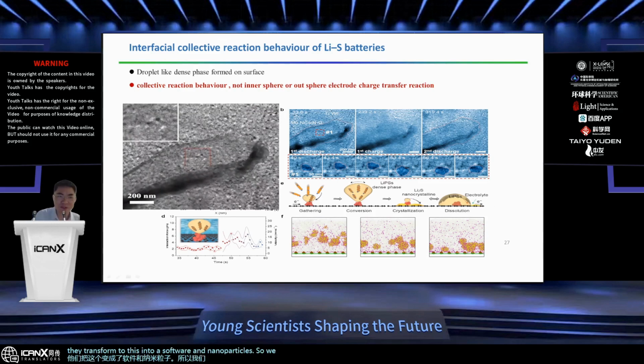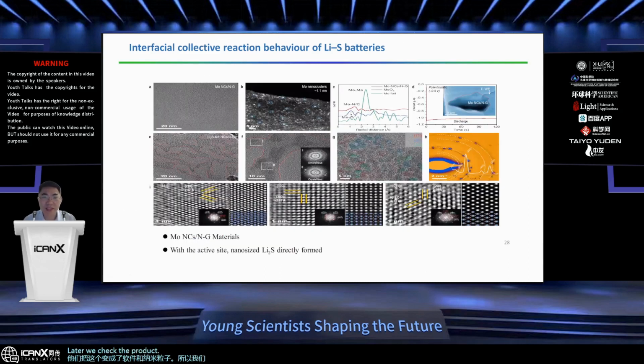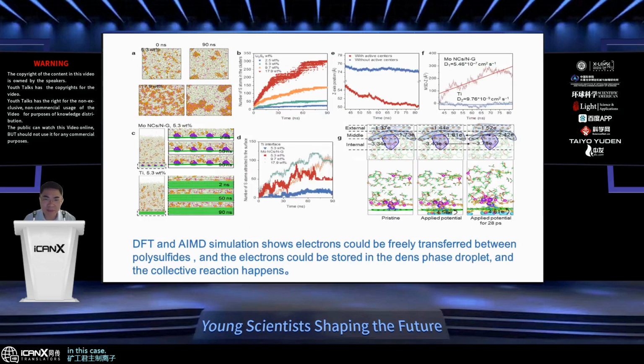Later we checked the product, and we find that they directly form the lithium sulfur. Previously, on the bare electrode, without the active center, the surface materials go through step-by-step transformation. They form polysulfide molecules, like the Li2S2 minus ions. In this case, the DFT simulation also shows that the electrons could be freely transferred between this polysulfide and this. Also, these electrons could be stored in this kind of dense phase droplet. This proved what could be happening inside of the dense phase.